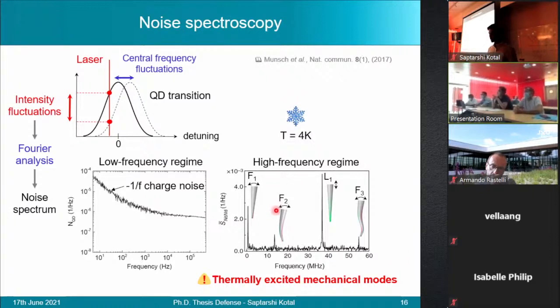Here, F1 represents the first fundamental flexural mode, where the trumpet oscillates from side to side. F2 and F3 are the second and third harmonic of the flexural mode. And L1 is when the trumpet extends and contracts vertically. Now, even at 4 Kelvin temperature, this experiment showed that there is enough thermal agitation in the system to be able to thermally excite these vibration modes.